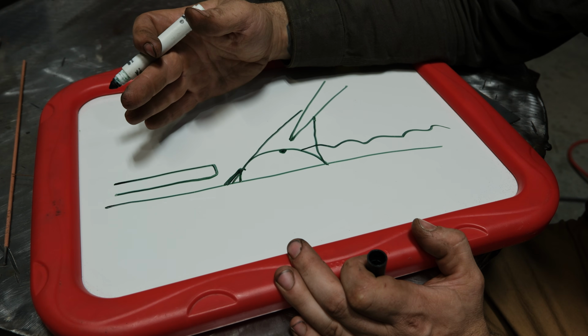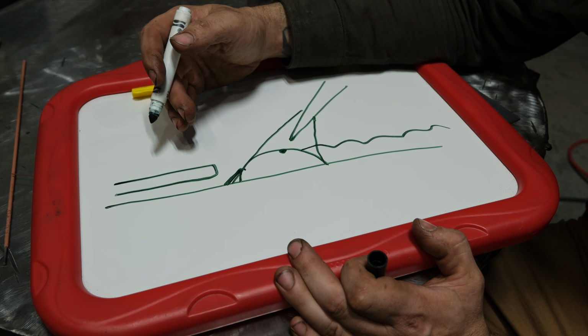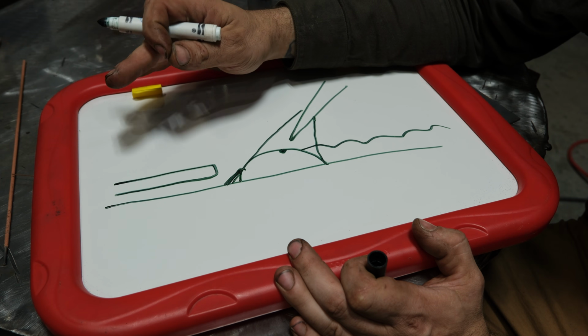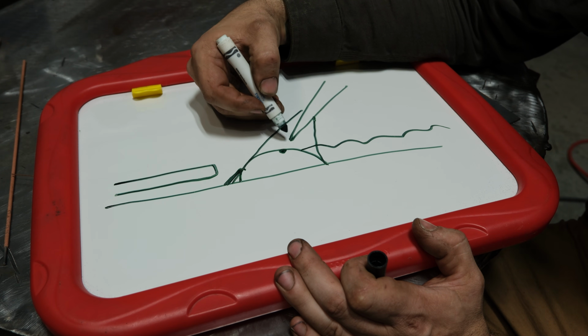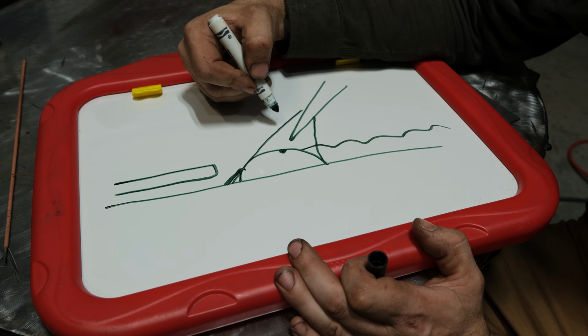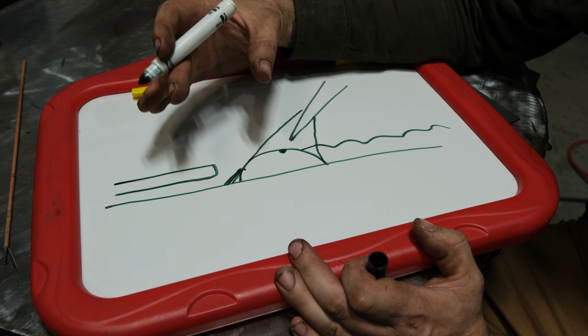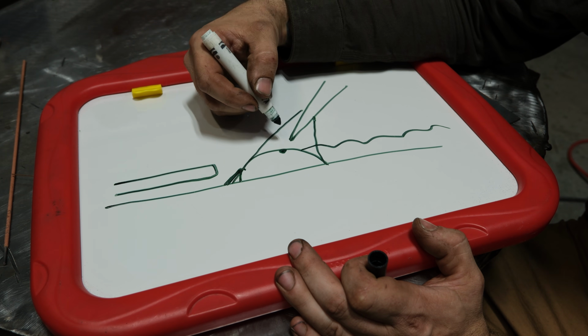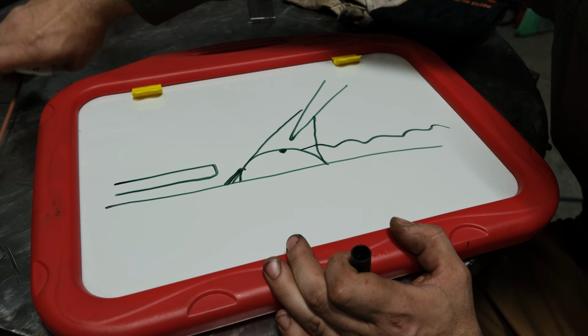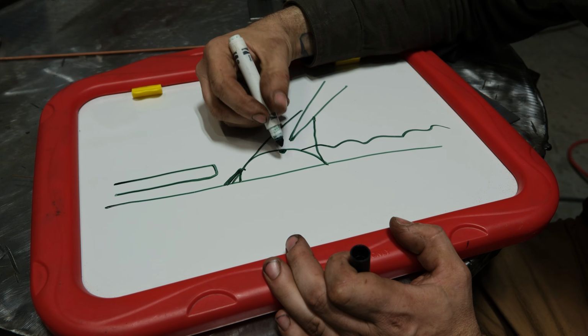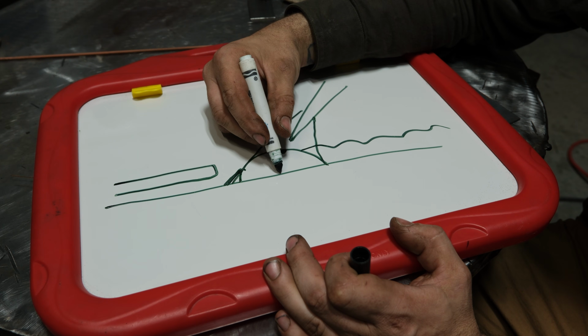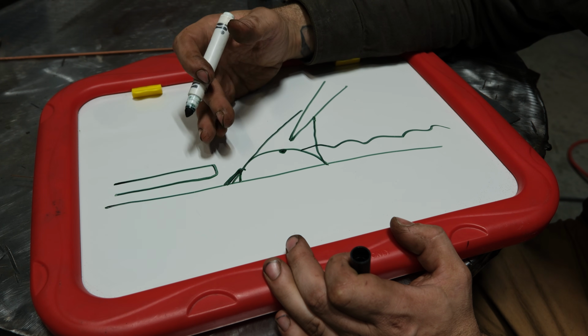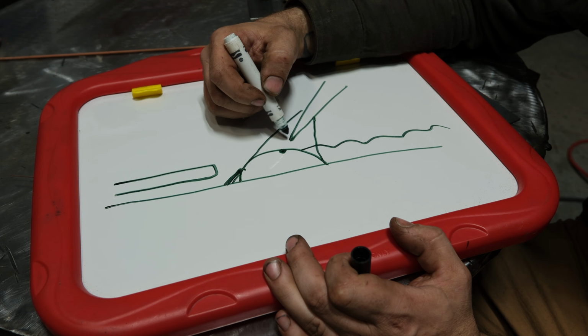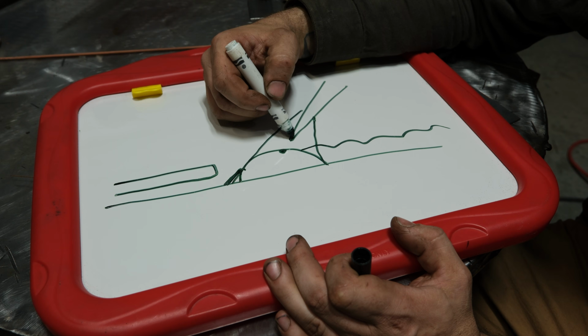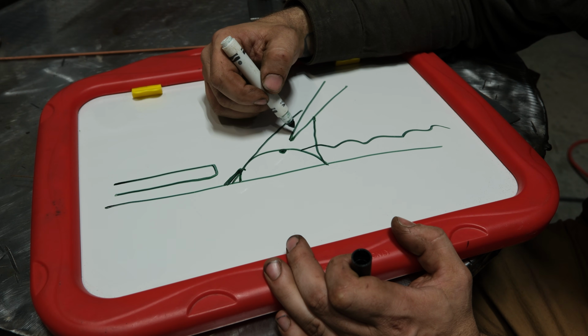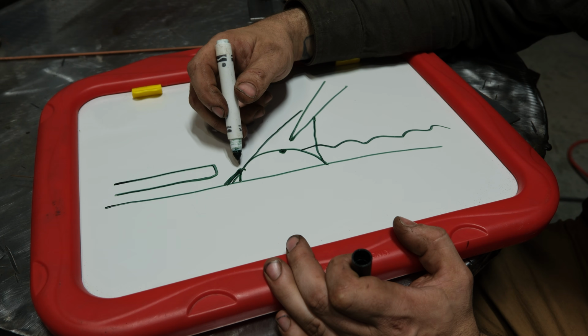Guys that I've trained before, what I notice is I tell them that and don't give them a scale of how little it is, and they end up lengthening the arc like an eighth of an inch while they're adding filler, and now your arc cone is all out of control and your amperage is all off, etc. You get the picture. So as you add filler, as you push this rod in, a slightly longer arc gap as the puddle rises. Now I personally, at the skill level that I'm at, I don't really raise it much except on aluminum. On steel, I just hold a slightly longer arc gap, assuming I'm adding filler.